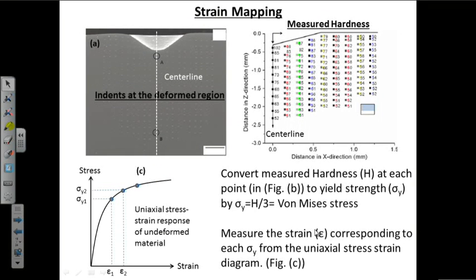I will give one example here. This is the actual macro indent which was performed on the surface of a material, and that macro indent caused enormous amount of plasticity in the subsurface of the material. So, this entire region is the deformed region, and we have done a series of micro indents in this region. At a fixed depth, we have done indents along the width of the deformed region, and we have repeated that method at various depths. After we perform these indents, we measure the hardness values, and those hardness values are plotted in this graph. Only half portion of the indent is shown here, and you can see that the hardness values are greater in the regions which are close to the macro indent. The farther we go from the indent, the more the hardness values reduce.